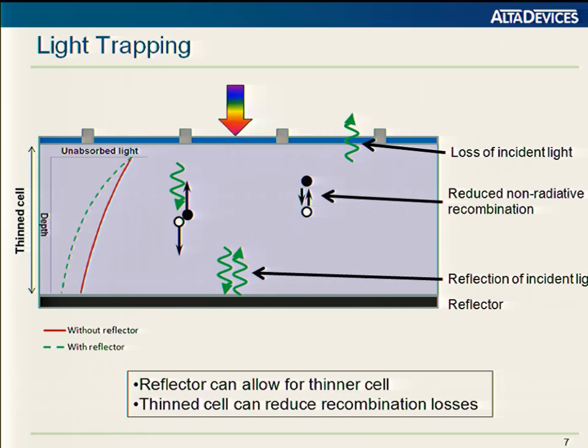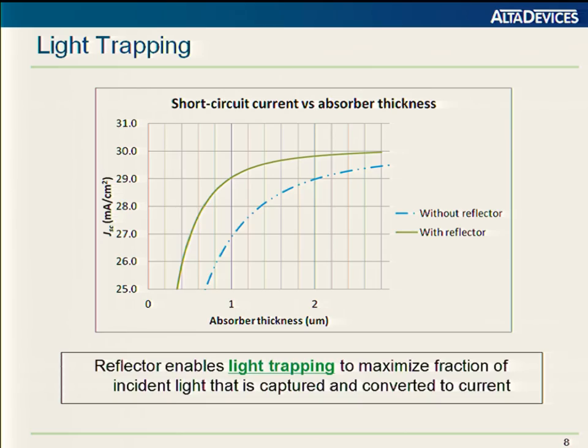We then lose some light. When you make the cell too thin, you start to lose light out the front side of the cell, the red light that didn't get absorbed even with two passes. You straight away can improve the performance by the fact that you have reduced the amount of semiconductor material in the cell. So the non-radiative recombination rate is reduced simply by that fact. But there's an additional mechanism going on that I want to talk about.